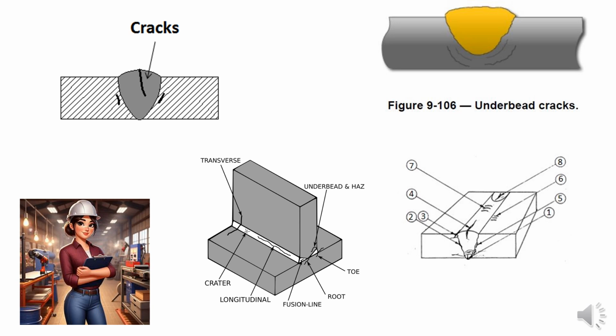Stress relief and post-weld heat treatment. Sometimes after you weld, the metal is still under internal stress. These stresses can make your weld more prone to cracking later on, especially when you've got a high-strength steel. This is where post-weld heat treatment, PWHT, comes in. PWHT involves heating the welded structure to a certain temperature and then slowly cooling it to relieve these internal stresses. But be careful. Reheat cracking can happen in steels with high amounts of vanadium or molybdenum, which form carbides that can cause grain boundary cracking if not treated properly. So like a swordsmith tempering steel in the fires, you need to control your heat treatment with care.